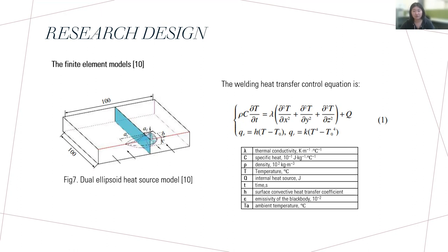First, we calculate the temperature field using a nonlinear heat conduction equation to determine temperature distribution during welding. Then, we apply this temperature data as a boundary condition to our stress field model, which calculates the residual stress.